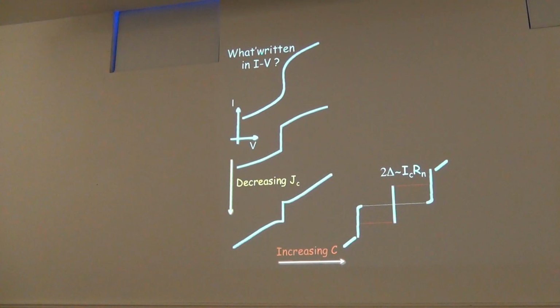This is an IV curve of a weak link, typical rounded shape this way. You would measure the same with the low angle bicrystal YBCO junctions. If you change the angle, or in this case, if you start working with a barrier, you start seeing a rounding. But finally, when you increase the misorientation angle, or for a junction, when you have a barrier, you pass to this characteristic shape of the RSJ model that yesterday was outlined by Dieter, and we will briefly mention now as it's necessary for our aims. Again, here we are somehow decreasing JC.